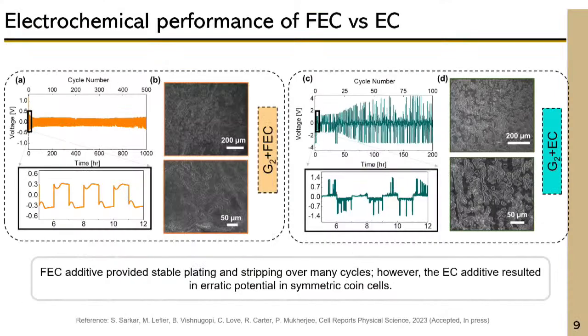Now let's take a look at the performance of these two cases. In the first case, we were able to stop the dendrites and we also got a very smooth profile - that's what we wanted. In the next case, we were able to stop the dendrites, but the voltage pattern is all erratic - not good, not what we wanted.